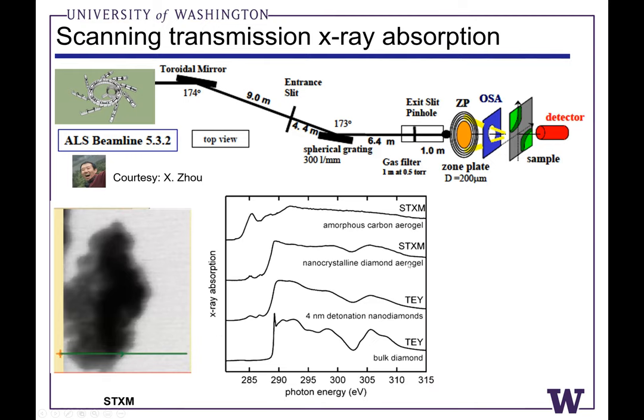This is a spectrum of the nanocrystalline diamond aerogel. This is a spectrum of the amorphous carbon starting material that we've started with. And you can see really quickly a dip in the carbon 1s to pi star graphitic absorption peak going from amorphous carbon to nanocrystalline diamond. You can also start to see this dip in the X-ray absorption spectrum at about 302 electron volts. And this maps onto the so-called second gap in diamond's electronic density of states. And so this is compelling evidence that we have a microstructural change in the phase of the carbon from amorphous to diamond phase. This pre-edge feature is something that I'd like to return to later on in the talk.